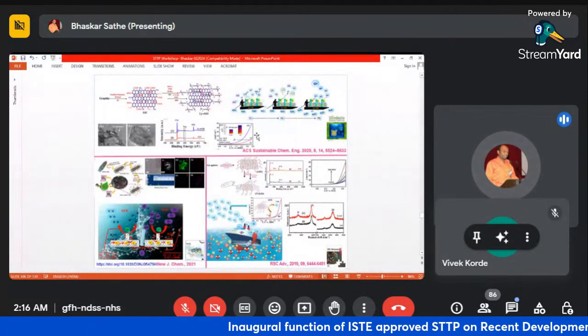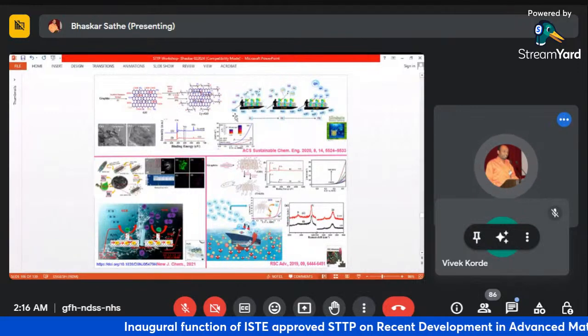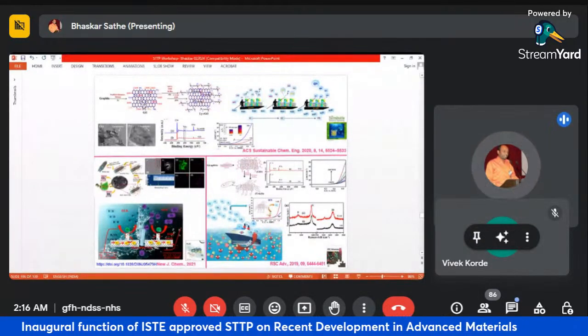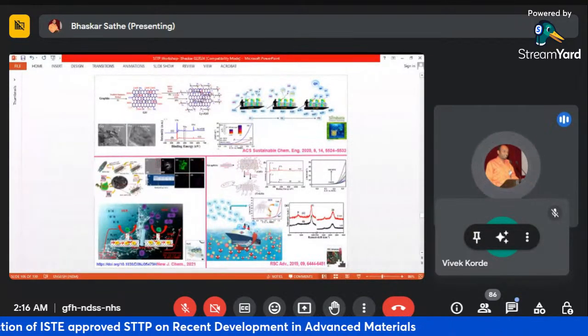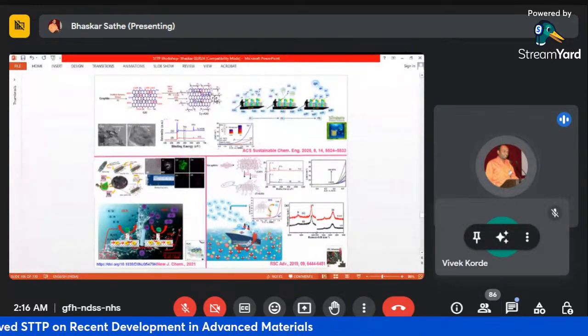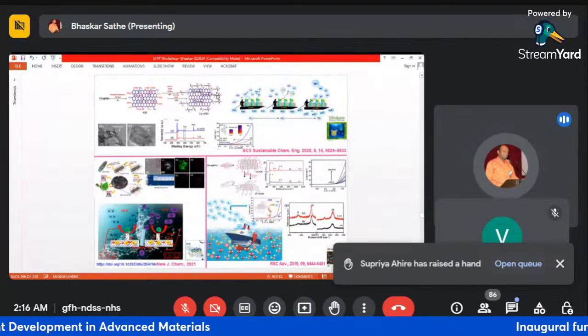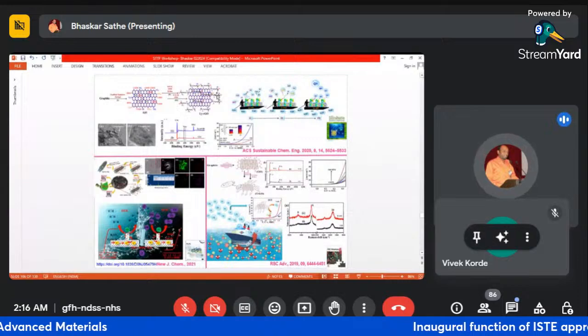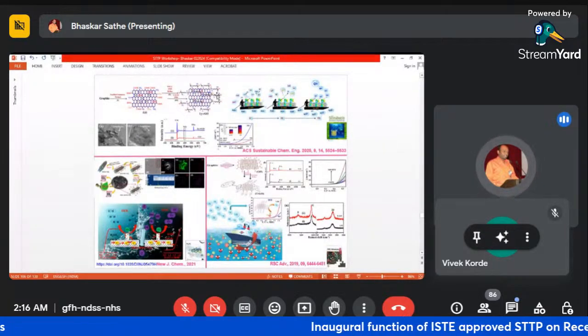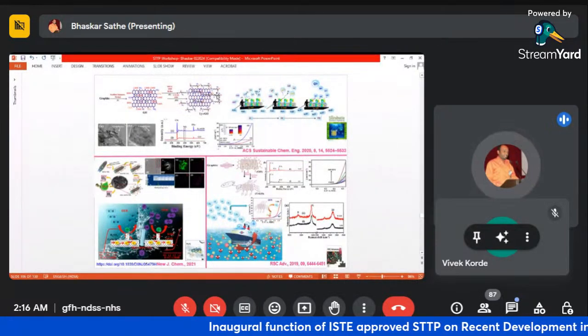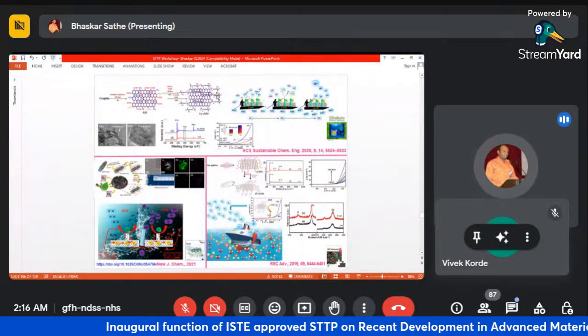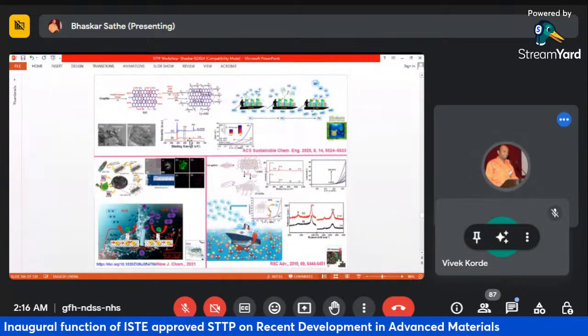So keeping that in mind, what we have done is decorate this with molecules which have active centers, like amino acids, which we have used systematically. One end we have coupled with the graphene, and the other is kept open for the oxygen and hydrogen containing species to interact to show the performance.